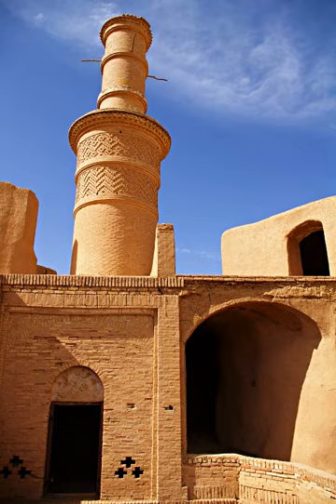When the block has been made from stabilized earth, which contains cement, the concrete must be given perhaps 3 weeks to cure. During this time the blocks should be stacked and kept from drying out by sprinkling water over them. This may be a problem in hot, dry climates where water is scarce. Closely stacking the blocks and covering them with a polythene sheet may help reduce water loss.